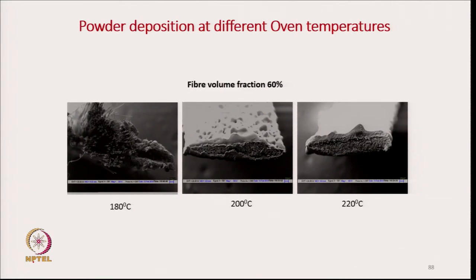So we can see here the improper powder deposition; it is peeled off at 60% volume fraction. At 60% volume fraction, the fiber volume is more, and it is severe. At 180 degree Celsius, the effect is much more severe than at 50%. At 50%, the fraying of the carbon filaments was not there, but at 60% volume fraction, that means the polypropylene coating was 40%. So at lower volume fraction of the polypropylene, it was much more severe.